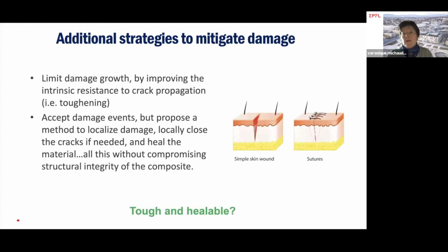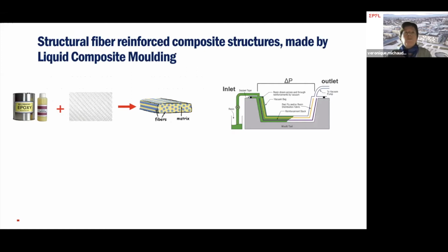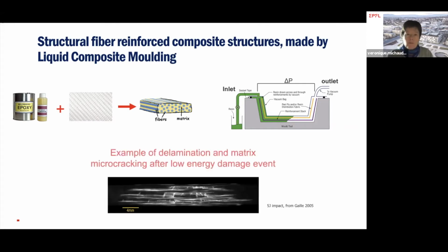So it's a little bit like a skin wound that you would have. And by adding sutures, for example, you can actually help the crack to be closed if it's too big, or if it's not big, it would simply heal by itself. Of course, we're not talking about skin here. We're talking about structural fiber reinforced composite structures, in particular those made by liquid composite molding, which requires a resin that is typically a thermoset epoxy, could also be a thermoplastic, then fabric, and by infusion, for example, or RTM or other processes, you mix the fibers and the matrix to create the composite.